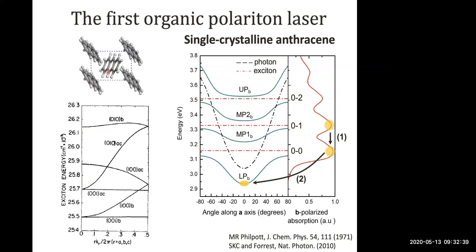The interaction between these molecules leads to a Davydov splitting of the low-lying exciton band. And the lowest lying band is this band which is polarized along the B direction of the crystal. And if you look at the dispersion relation, because of these vibronic replicas, you actually end up with a manifold of polaritonic states along the B direction. So we have this lower polariton branch, a few middle polariton branches, and an upper polariton branch.